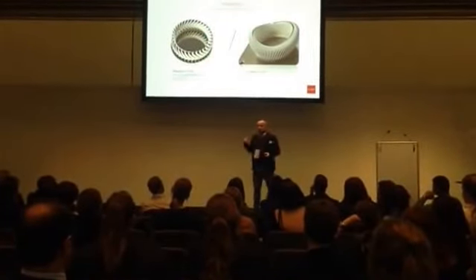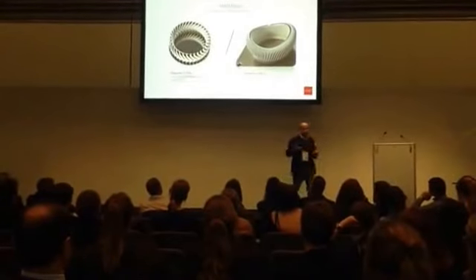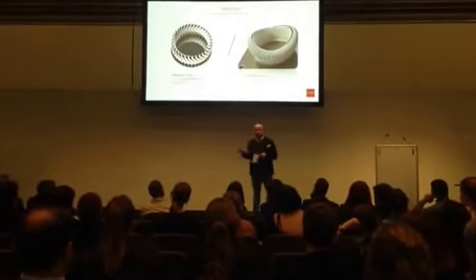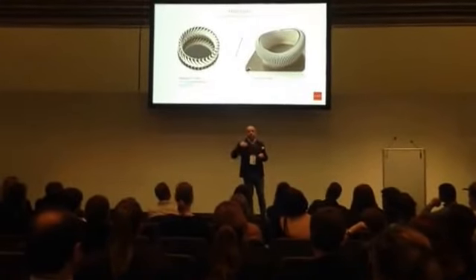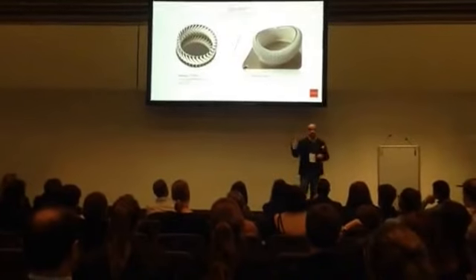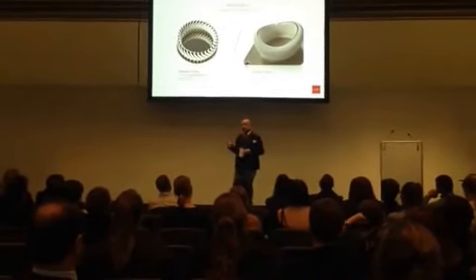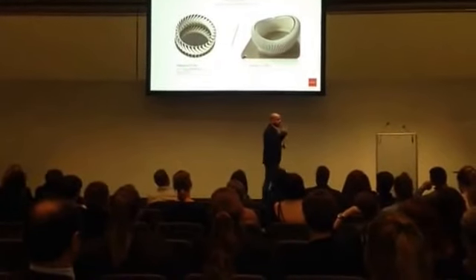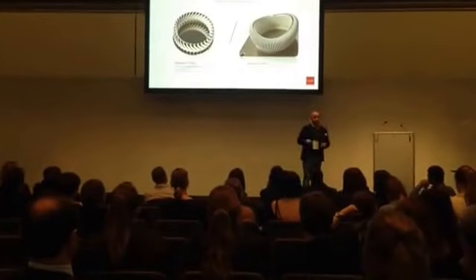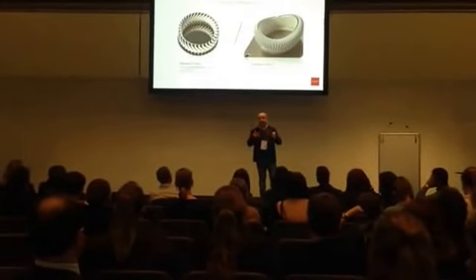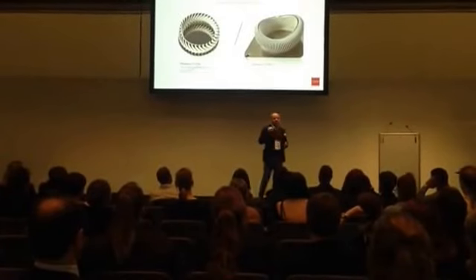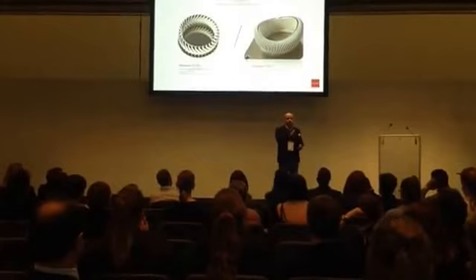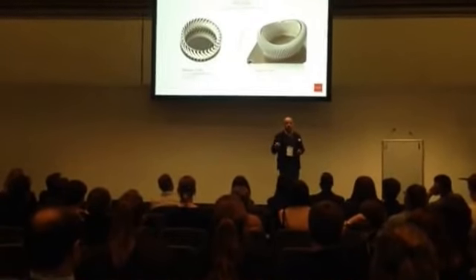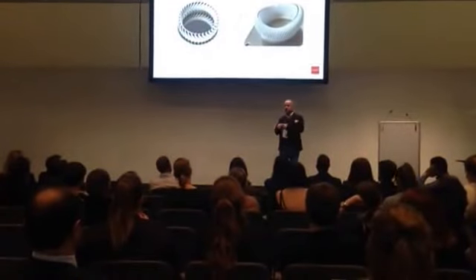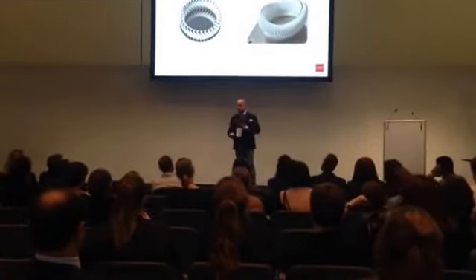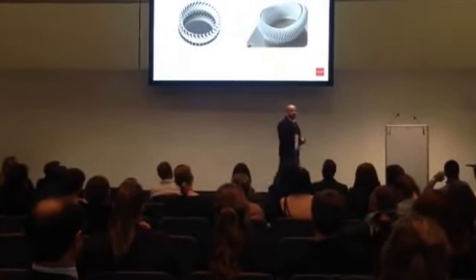Another opportunity from the material point of view that I wanted to focus on here is platinum and titanium. Compared to other precious metals like gold, platinum, for example, loves the laser power very much. Its thermal conductivity and electrical conductivity are much lower than gold, and this means it's absorbing a lot of the power that the laser is giving. So just to give you a very practical example, to melt, to scan, and to print platinum, we need 20% less energy, even if the melting range of platinum is something like double that of gold. That's why platinum loves the laser very much.